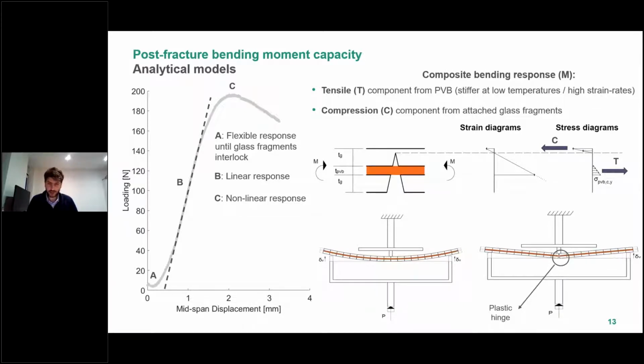A plastic hinge eventually forms when the top glass layer crushes in compression, resulting in a collapse mechanism for the simply supported specimens tested. The moment capacity for this stage is derived by taking moment equilibrium about the plastic neutral axis. In the final stage, the PVB tears when the failure strain is reached. The response, however, is anticipated to be more ductile under blast events, as the low temperature results in a stiffer adhesion bond that inhibits the delamination of the glass fragments and causes brittle fracture of the PVB.